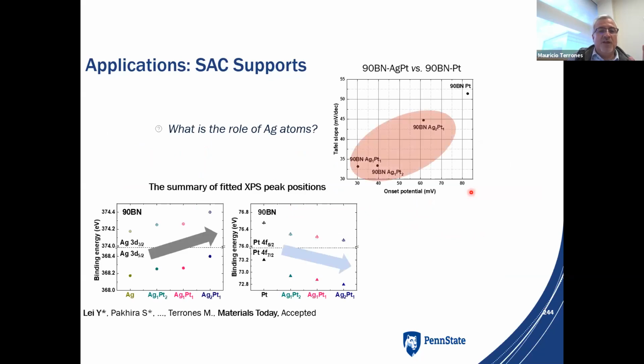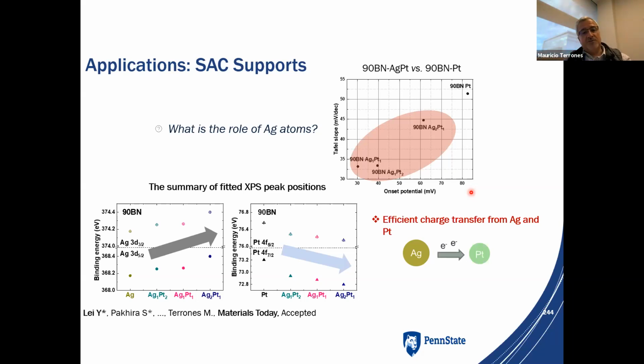I think we can do many things with these systems. We have seen that the stability of these clusters with boron nitride is very high, so you can heat it at higher temperatures and the clusters remain there. So I think this could be used as a new support for catalysis. But again, this is driven by defects, right? So you create some defects, you improve the reactivity, and then you can reduce salts and make these clusters, very small clusters, or even single atoms of these metals.